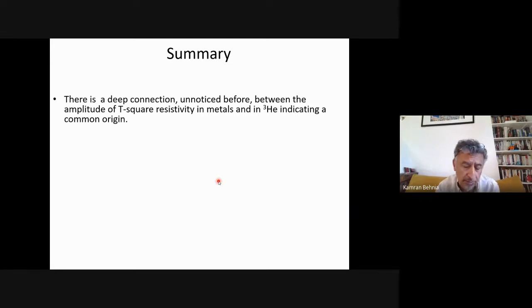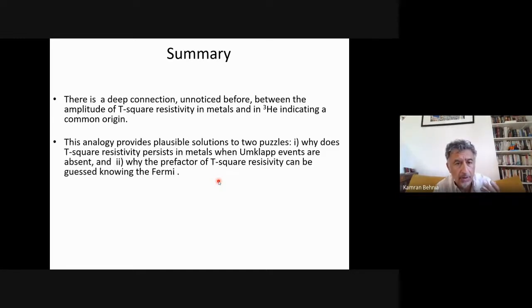I would like to begin by just summarizing it in this way: I think the main message is that there is a deep connection, which was not noticed before, between the amplitude of T-square resistivity in metals and the amplitude of T-square thermal resistivity in helium-3. This, in my opinion, indicates a common origin. This would explain why T-square resistivity persists in metals where Umklapp events are absent, and why the prefactor of T-square resistivity can be guessed knowing the Fermi energy.